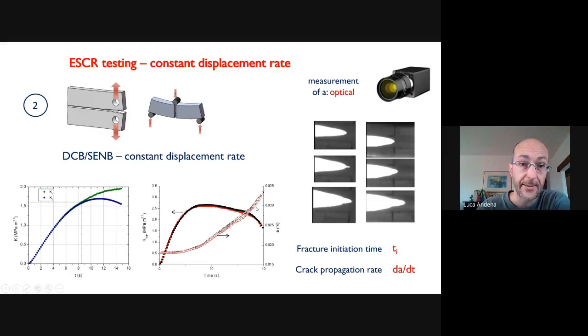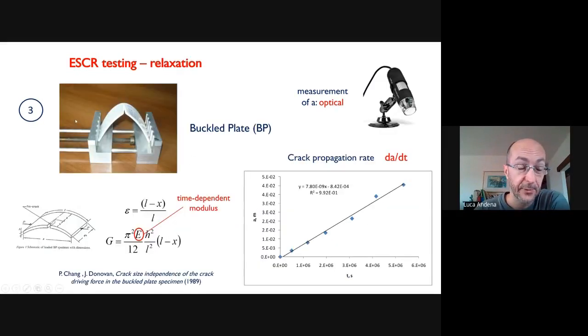And the buckled plate configuration is a bit more peculiar. Here you apply a constant bending to the plate, and you start with mode 3 conditions in which the crack driving force, which is given by this energy release rate term, only depends on the material modulus and the geometry.